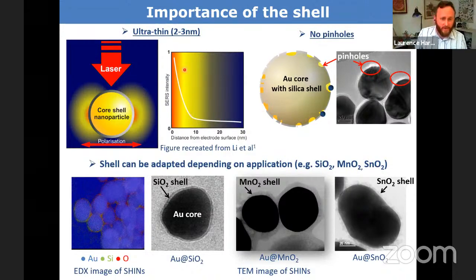But if you have a shell too thick, then you don't get very good signal enhancement. So there's a sweet spot between 2 and 3 nanometers of thickness where you avoid pinholes, but it's thin enough to still give an appreciable signal enhancement. And we have some transmission electron microscopy images here of some of these shells.